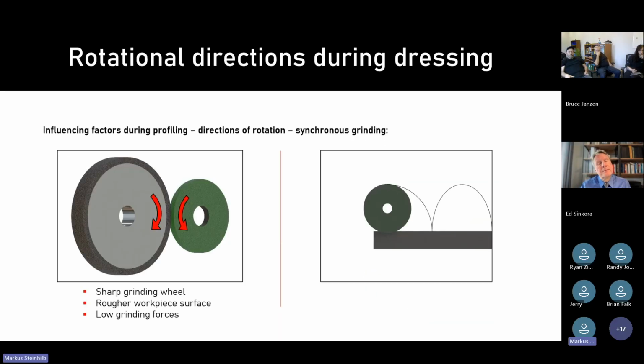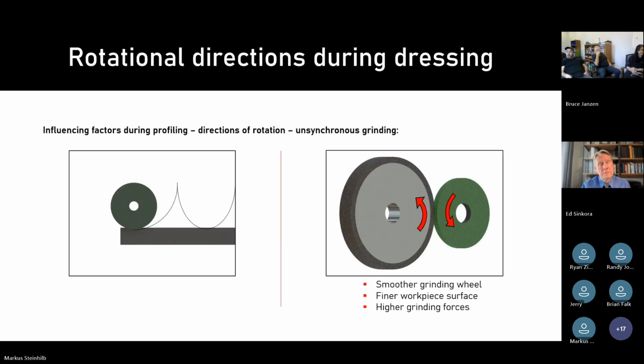Also, the rotational direction affects the performance of profiling. By choosing a synchronous direction, the effective cutting force is significantly lower. And so we achieve, as you see here, a sharp grinding wheel, a rougher workpiece surface, and low grinding forces. By turning the rotational direction around into asynchronous, we generate a smoother grinding wheel, a finer workpiece surface, and higher grinding forces.